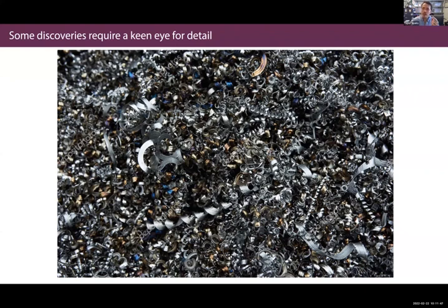And he tries one, and it was unremarkable as a material for a gun barrel, so he skips it, but he comes back a couple weeks later, and it hasn't rusted, and everything else was rusted. He sees some speckles of shine, as the story goes, right? And so he's looking back in his notes and he realized that, well, that was an alloy that had over 13% chromium, and thus we have the birth of, they called it rustless steel, I think is what they called it originally. We know it now as stainless steel, right?